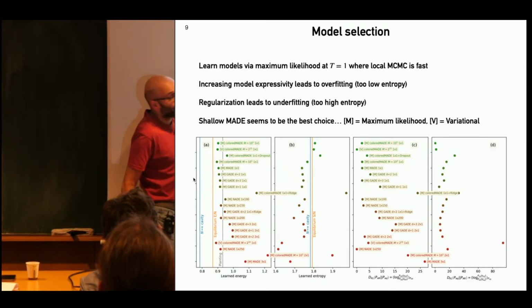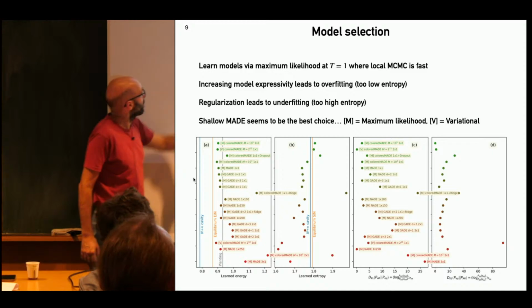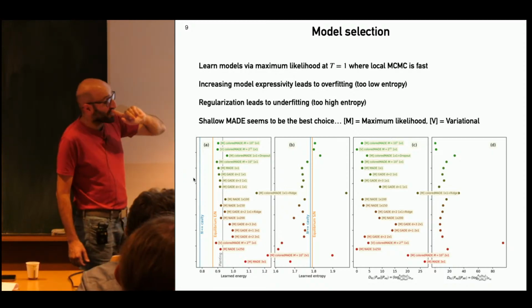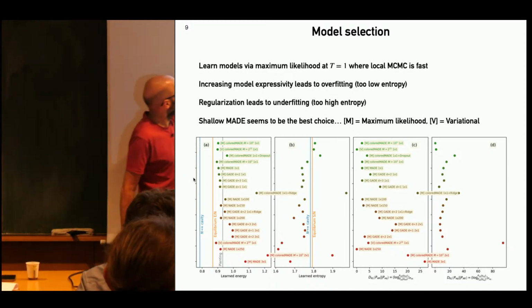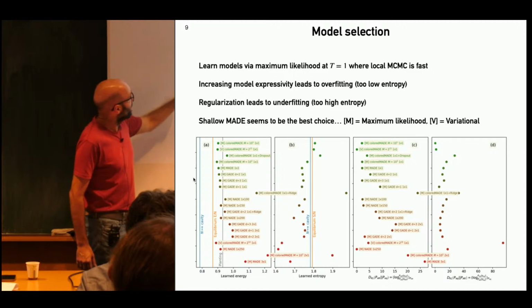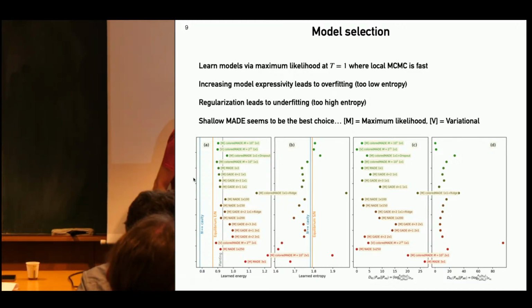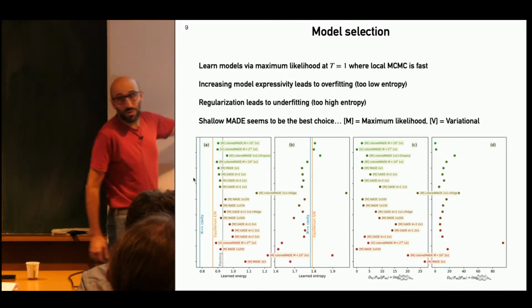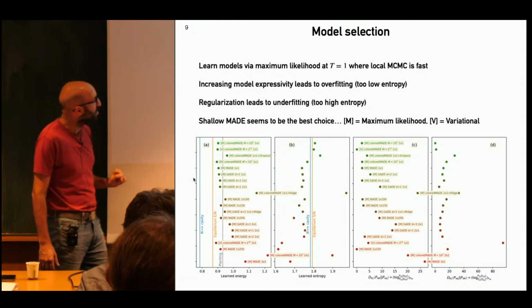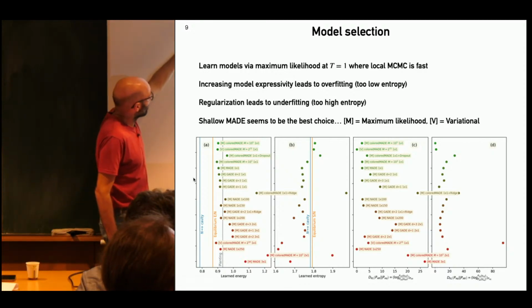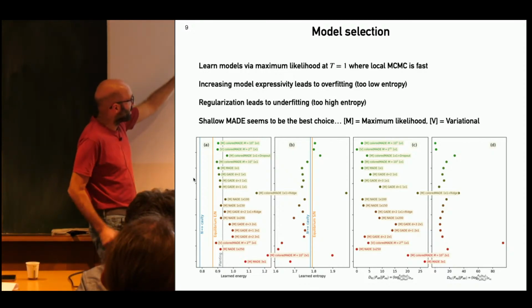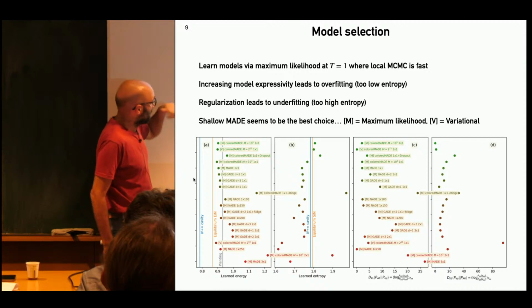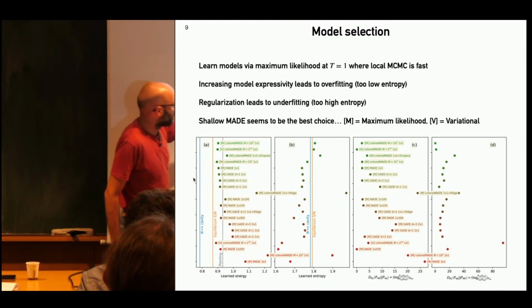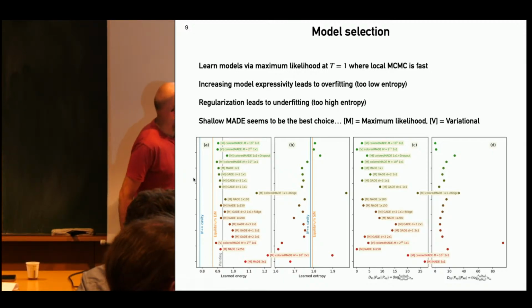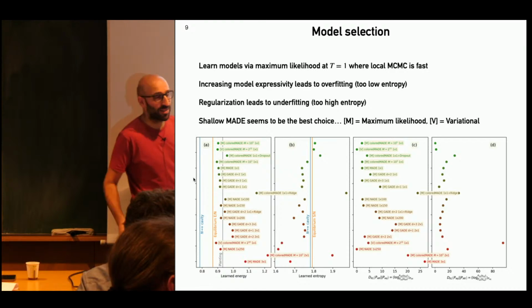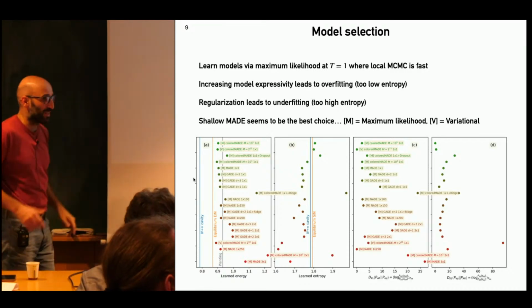You need to have enough training data to get this. If you try to put regularization, for example dropout or ridge, what you see is that the entropy increases and the energy also increases. So it doesn't seem to be good. If you try to increase the expressivity, so you put more parameters, again it doesn't seem really good. Also, in some cases, for example here, you get a too low entropy. So it seems that you are overfitting and you get mode collapse.